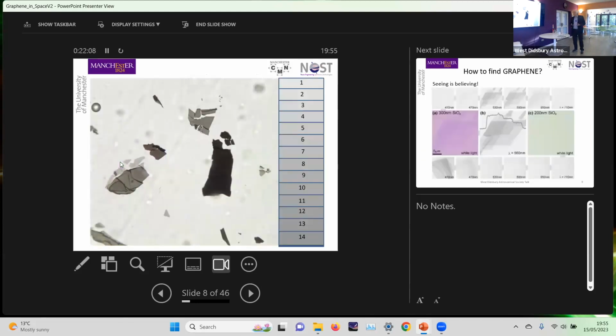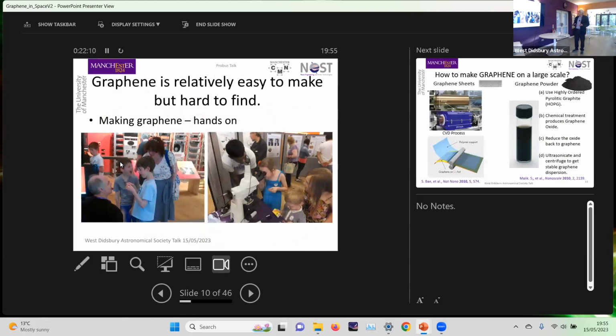It was a student of mine that developed a model that showed that the thickness of that oxide is quite critical in seeing the graphene. Also, the color of the light that you're using is quite critical as well. So it was in a way somewhat fortuitous that he was ever able to see it in the first place. So if we'd had 410 nanometer oxide, he wouldn't have seen the graphene. And we may not be where we are today. And of course, it's so easy to make. This peeling technique is so easy.